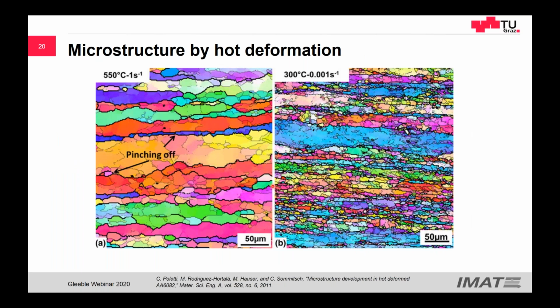This is the most important thing I think that we can achieve when we cool down very fast, and this is that we can freeze the microstructure. The freezing of the microstructure is not interesting for the industry. They cannot achieve this very fast cooling rate. But it's important for us so that we can see what happens in the microstructure. If we leave this microstructure at a given temperature cooling down very slowly, we will have static recrystallization. And then we cannot really understand what happens during hot deformation.